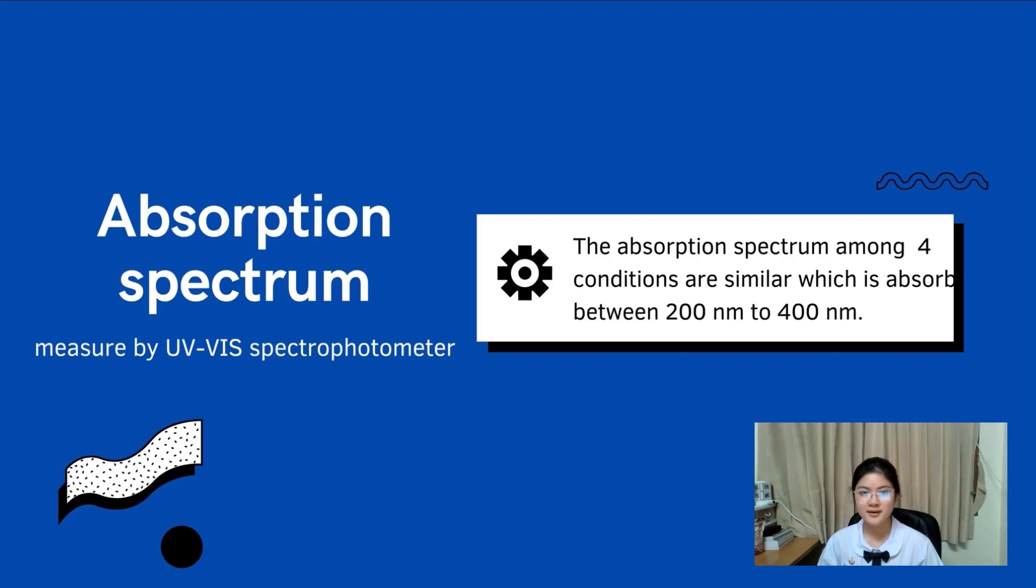And for the absorption spectrum, we found that all four conditions are similar, which is between 200 nanometers to 400 nanometers.